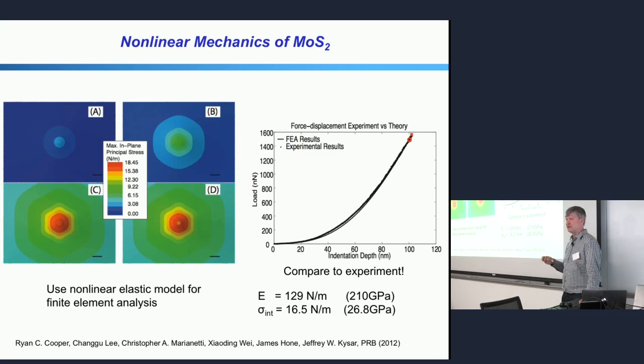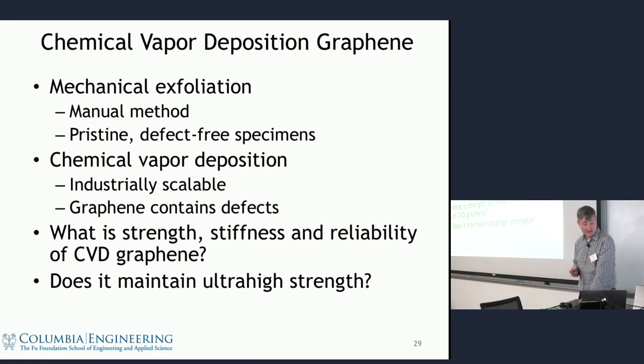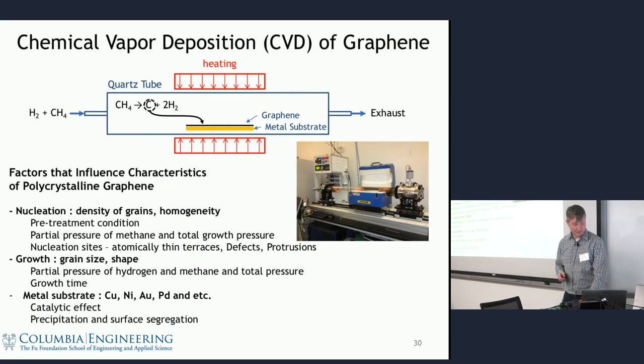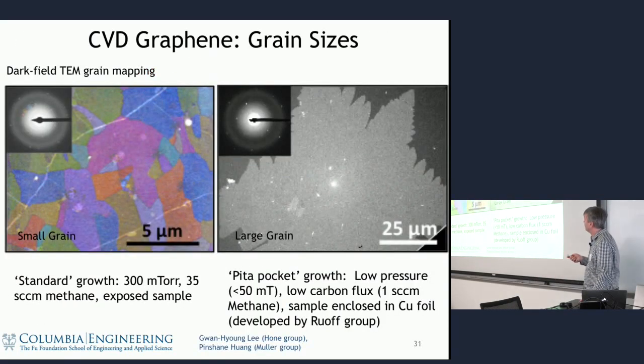What happens if now we start adding defects to the mix? And so we did a couple experiments about that. The first one was to look at CVD grown graphene, where you have grain boundaries. And so the question is, once you have grain boundaries, is it going to be as stiff or not? So I think I'll skip over this. Just to show some images, this is again grain maps with color mapping and a TEM of two of the types of samples we looked at. We called this small grain, roughly micron-sized grain, and large grain, where we have tens of microns of the grain.